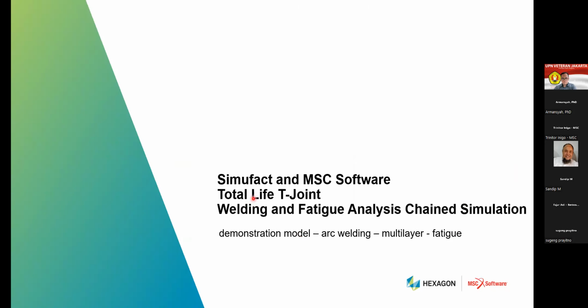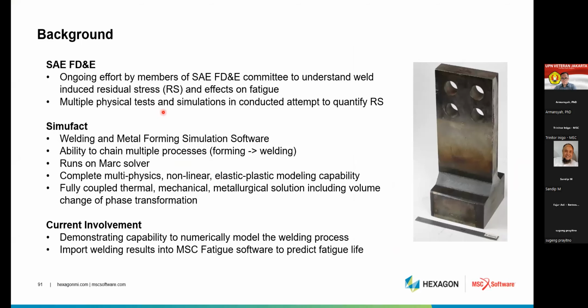Now we'll see the case study for the fatigue analysis. This is an ongoing effort by the SAE FD&E committee to understand the weld-induced residual stresses and their effect on the fatigue life of the component. It will showcase after how many cycles this component will fail, or the damage or the crack will happen, under the operating conditions.